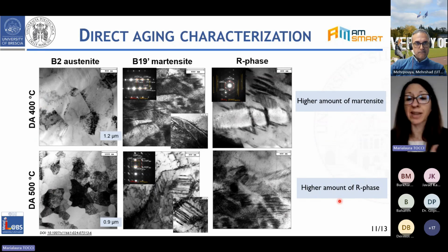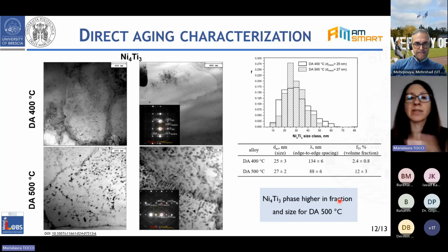phase, that, as we said, usually suggests the presence of precipitates, of Ni4Ti3 precipitates that were actually observed. As you can see in these images, they have a lenticular shape, and as you can see also from the diagrams, comparing these precipitates and their distribution in the samples after these two aging treatments, we found more or less a similar size distribution and a similar average size, but these precipitates were much more abundant in the sample treated at 500 degrees, indicating that the higher temperature treatment is actually more effective in promoting the formation of these precipitates, and in agreement with the more abundant R phase, as we said.